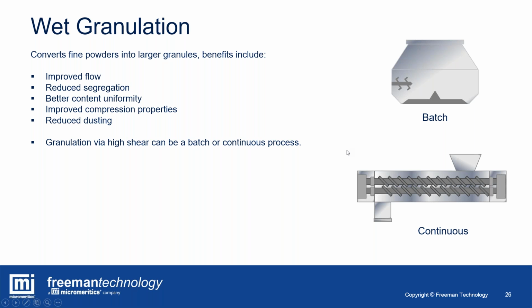In contrast to what I'm going to talk about shortly in the rest of this application, a continuous process whereby powder is fed into this hopper. You have a twin screw that kneads and conveys the material through the process as water is added, and out the other end comes a granule with certain properties depending on your configuration. But in both cases, liquid is introduced whilst the powder is being sheared.